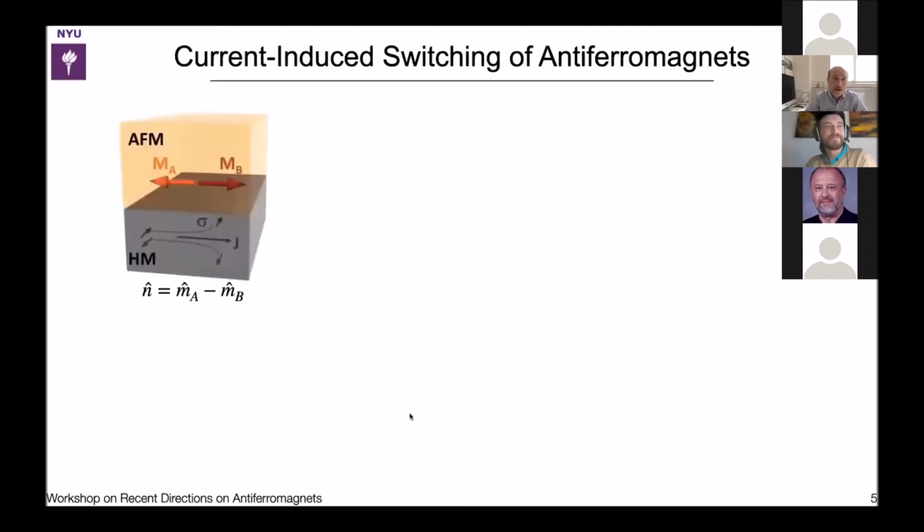So, introduction. I think the exciting thing here is that we have a mechanism to manipulate antiferromagnets that doesn't require huge magnetic fields and can potentially be very, very fast. It's very difficult to manipulate antiferromagnets, as you've heard earlier. Essentially, it's hard to couple to the staggered order. A magnetic field doesn't do this very effectively, especially if there are anisotropies and a reasonable Néel temperature.